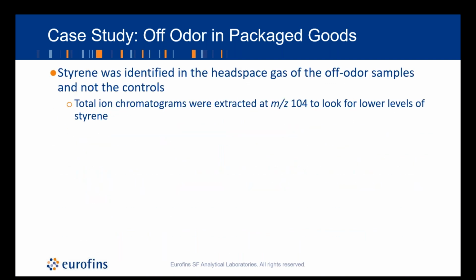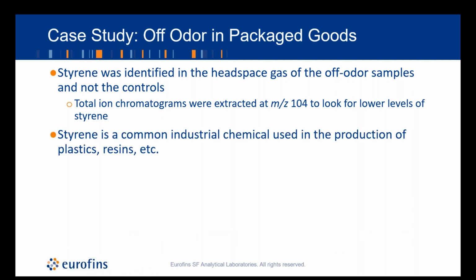So we did find styrene in all of our suspect packaging, which had the chemical off-odor. This compound is known for that odor, and it's also very common in industrial uses for the production of plastics, resins, and many other things. So in this case, they found that they had a contamination or leaching issue where multiple types of packaging had been contaminated with this chemical agent.